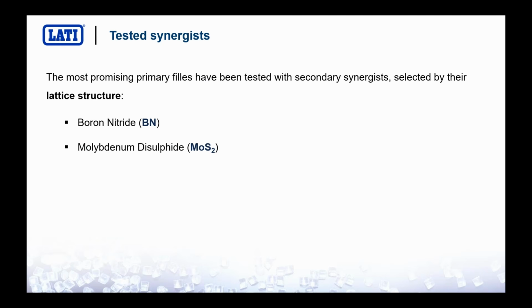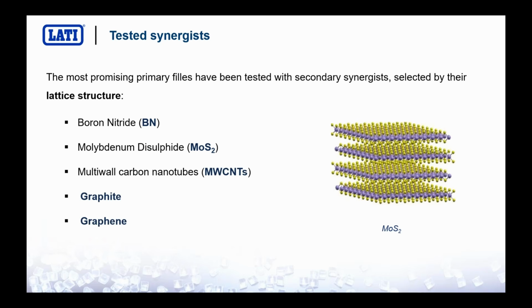Then we had a look also at the synergists. Also in this case, we tried to find something that from the literature can work as a synergist with a main filler. For example, a lot of lattice structure materials like ceramics, like boron nitride or molybdenum disulfide, but also some carbon-based materials like carbon nanotubes, which should help to improve the nucleation and so the hardness of the surface of polyamides and other semi-crystalline materials, and also graphite and graphene.